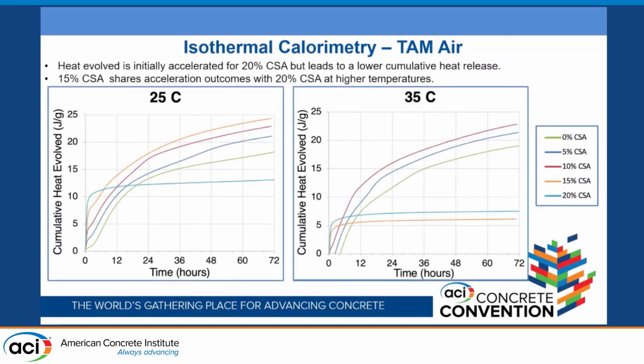So I want to start off by showing the cumulative heat evolved within the isothermal calorimetry. And you can clearly see that the orange line, or the 15% CSA replacement, had the highest cumulative heat evolved after 3 days, which reflects why we could see the higher compressive strength. It was more likely to have a longer amount of time hydrating at a higher rate.